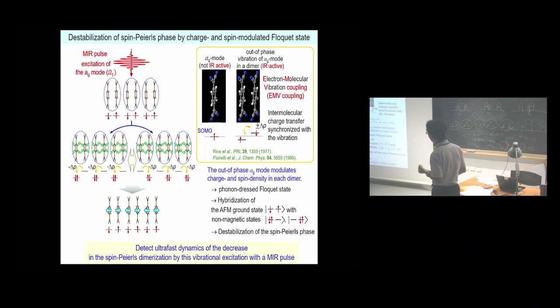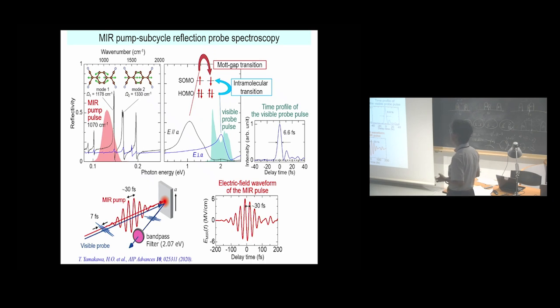Such an interaction between electrons and molecular vibrations is called electron-molecular vibration coupling. This out-of-phase Ag mode will modulate charge and spin density in each dimer and create a phonon-dressed Floquet state. It hybridizes the antiferromagnetic ground state with a non-magnetic state like this, and is expected to destabilize the spin-Peierls phase. Our purpose is to detect ultrafast dynamics of the decrease in the spin-Peierls dimerization by this vibrational excitation with a mid-infrared pulse. This is the experimental condition.